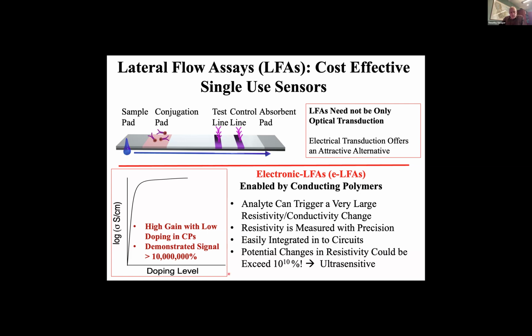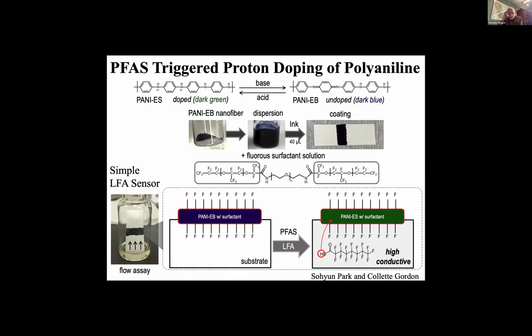However, if we put what is known as a conducting polymer in place of that optical band, we can make use of the fact that with a small amount of carrier injection into conducting polymers, that is holes in this case, we can get many orders of magnitude change in their conductance. In fact, these polymers often have ranges of conductivity with doping that exceed 10 to the 10. And so that's really a large signal. And so how we go about doing this is we work with a polymer called polyaniline here. Polyaniline is shown in the upper right as these radical cations, so it is actually conductive in this form. But if you treat it with base, you take away the protons from this, and you create a material which is an insulator. Okay, so we make an insulating version of this.